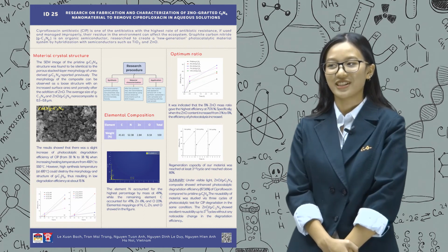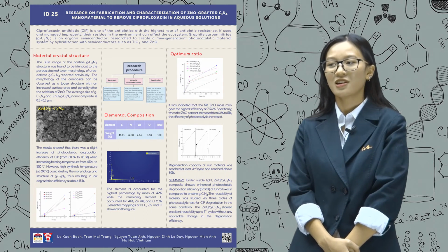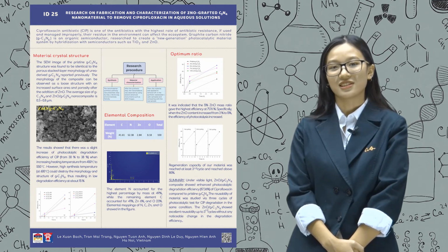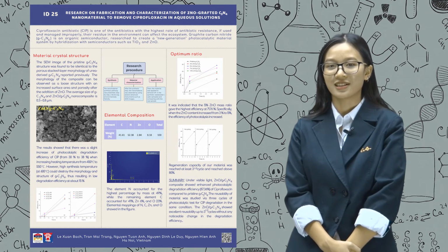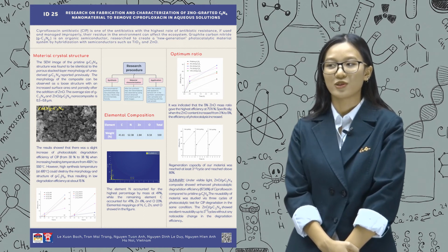Lastly, we have a summary. Under visible light, the zinc oxide/g-C3N4 composite shows enhanced photocatalytic degradation efficiency, with 87.36% of ciprofloxacin degraded, compared to pristine g-C3N4.